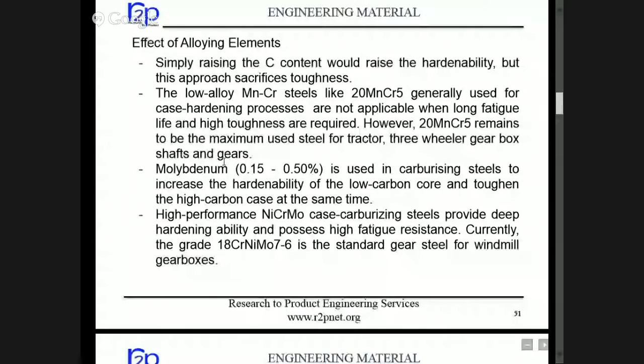But as we move towards the rear of the gearbox, in the final reduction stages, then we have to go for steel containing moly or nickel. Moly is used in carburizing steels to increase the hardenability of the low carbon core and toughen the high carbon case at the same time. High performance nickel chrome moly case carburizing steel, which you can say is the ultimate in case hardened steel, provides deep hardenability and possesses high fatigue strength. Currently, this 18CrNiMo7-6 is the standard gear steel for windmill gearboxes, you can say the most heavily loaded gearboxes.